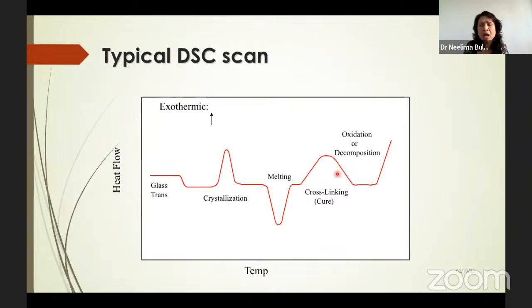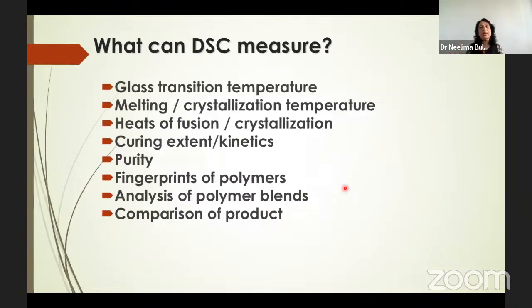Never, never, never allow your material to degrade or decompose in DSC because it will spoil your sample holder. And if you are doing cross-linking or curing kinetics, you will get an exotherm because that is the heat evolved. Whenever there is any exothermic reaction, you get an exotherm.